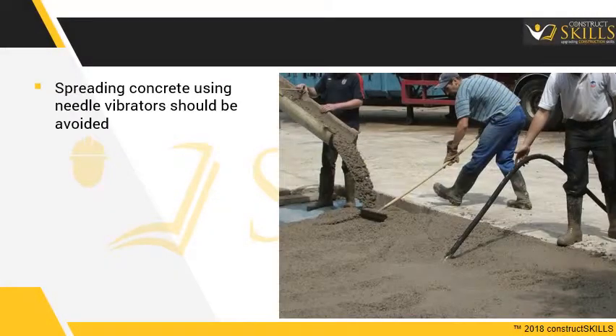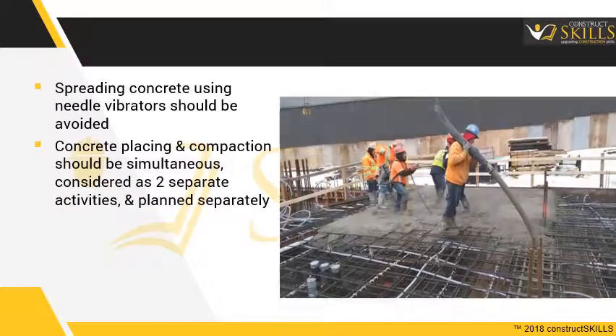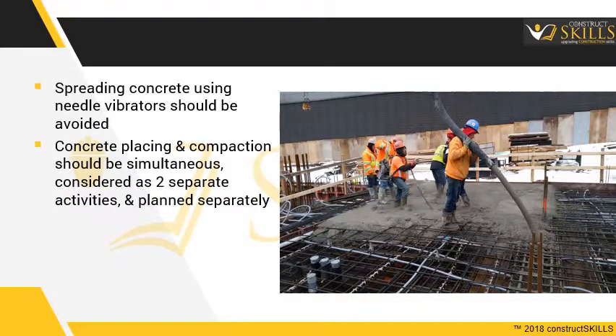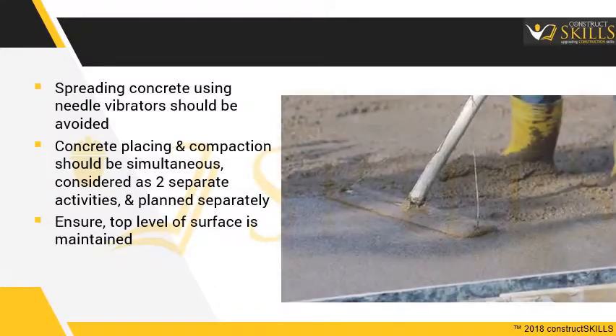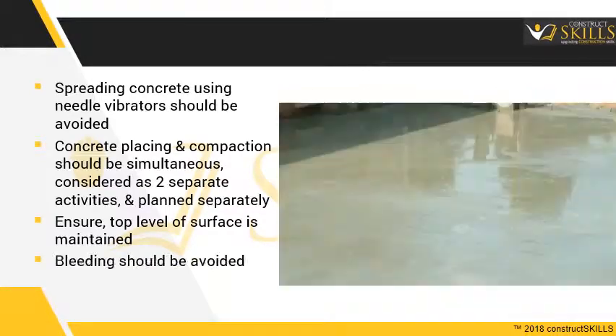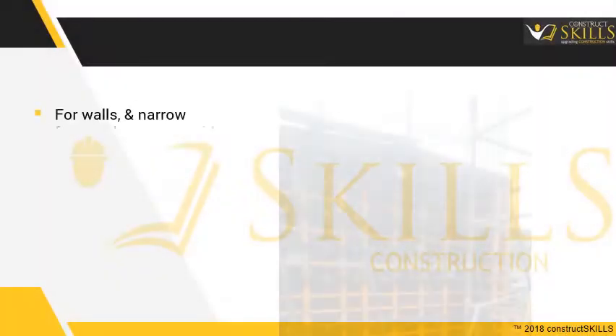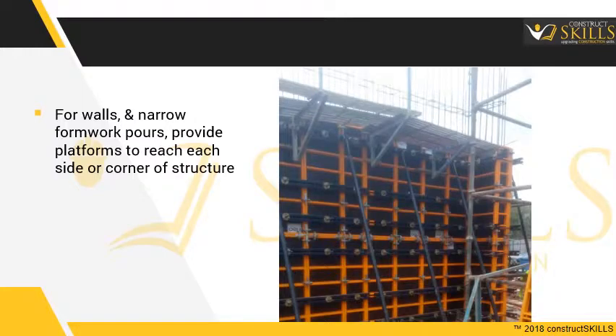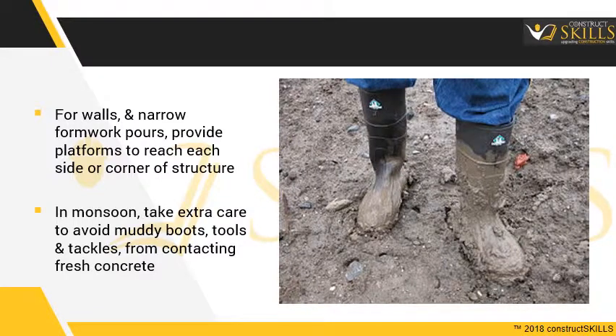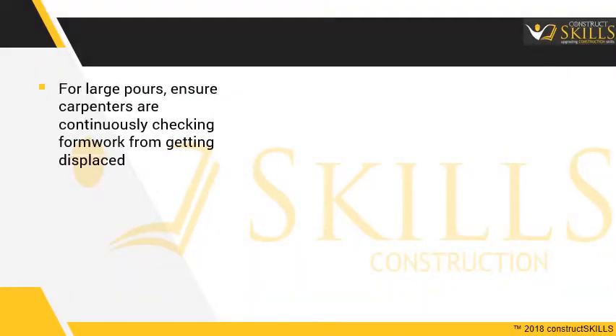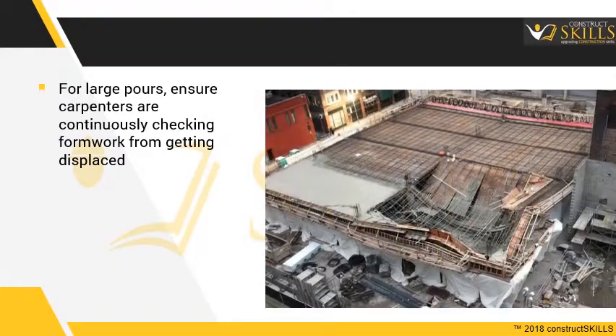Spreading concrete using needle vibrators should be avoided. Concrete placing and compaction should be simultaneous and planned as separate activities. Ensure the top level of the surface is maintained. Bleeding should be avoided, and excessive poker vibration should be avoided. For walls and narrow formwork pours, provide platforms to reach each side or corner of the structure. In monsoon conditions, take extra care to avoid muddy boots, tools, and tackles from contacting fresh concrete. For large pours, ensure carpenters are continuously checking the formwork for displacement.